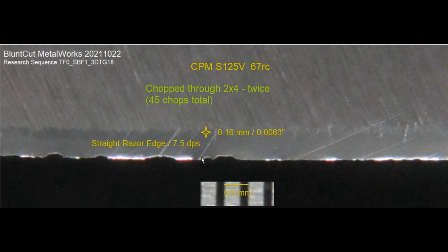But if you push the roll beyond, to the plasticity range, then you go to fracture. And these are the two fairly, the worst fractures on the whole edge right here. And versus the scale, here is 0.5 millimeter at this bar right here. So this is what we call microchip. If it was a chip without any sort of plastic deformation, then yeah, that's just brittle chipping. But when you chip after the plastic deformation, well, it's fractured. It's not a technicality, but that's what you usually call it.